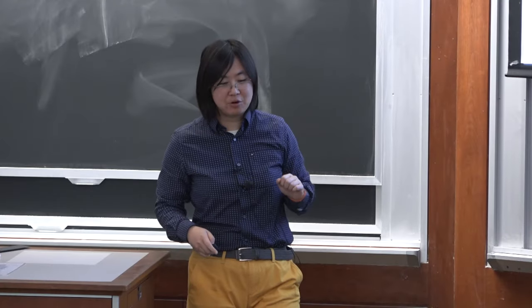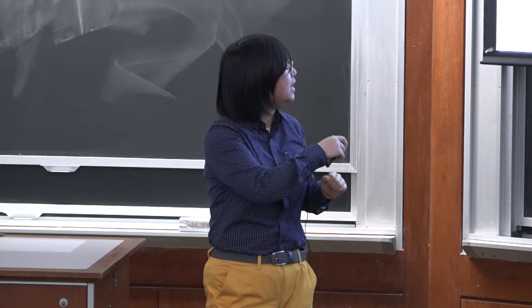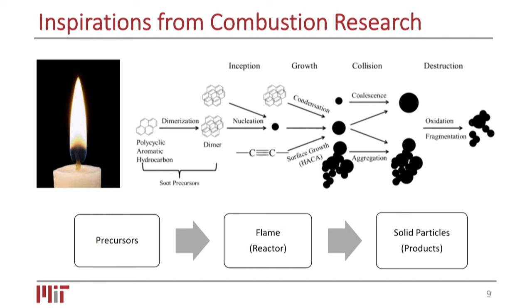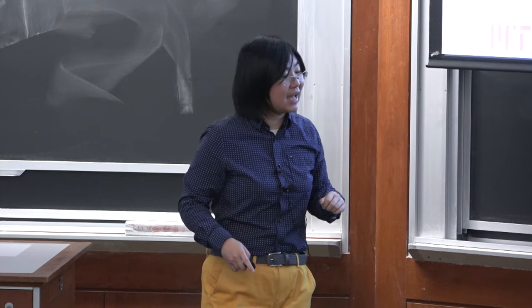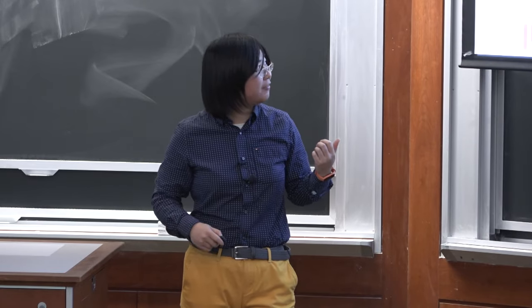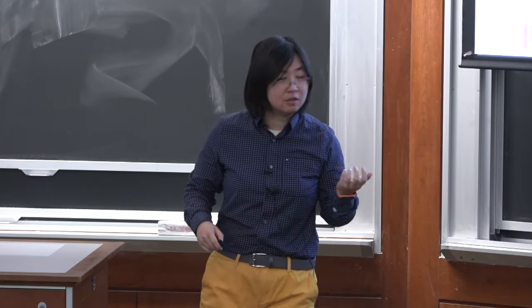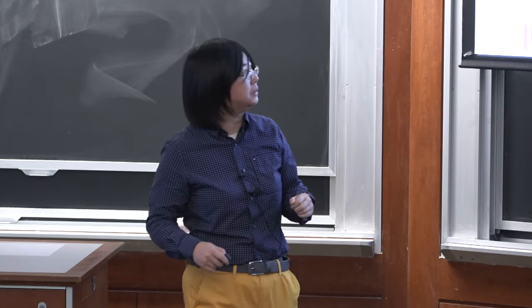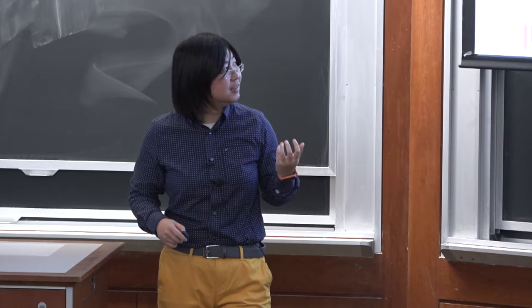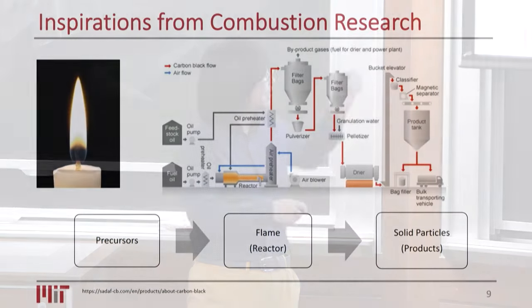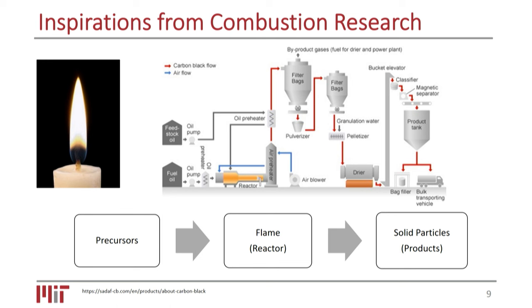If we summarize this process into a simple flowchart, we supply the flame with certain precursors. The flame works as a reactor, and via this high temperature process we can get solid particles. That is exactly the technology we have in mind, and it is also the technology used to produce a massive amount of carbon black and other commodity materials such as titanium dioxide, etc. It's by carefully selecting the precursors, controlling the flame as a reactor, and obtaining solid particles, metal oxides, or carbon materials of desired morphology and performance.